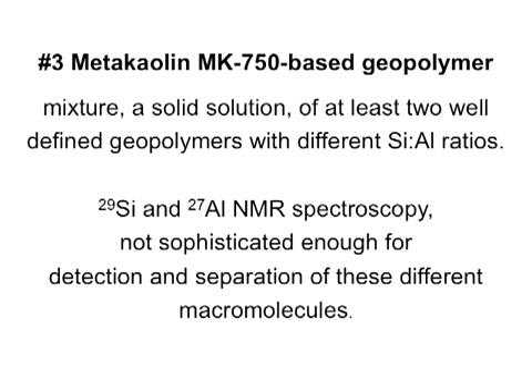We have seen that the result of the reaction of metakaolin is what we call a solid solution. It is a mixture of well-defined geopolymers with different Si/Al ratios, and so far nuclear magnetic resonance spectroscopy is unable to separate between the 2 or the 3 or the 4 that are constituting this solid solution. The only way is to heat up the material and wait until they crystallize, and then we get nepheline-type framework, carnegieite-type framework, leucite-type framework, and so forth. So we have to develop and invent a new way of detecting these phases more precisely.